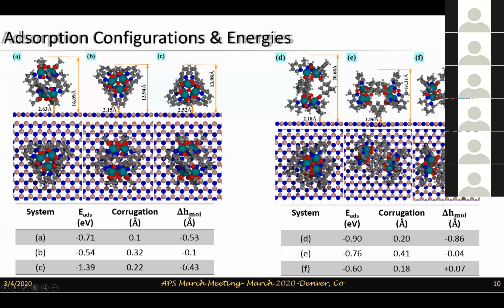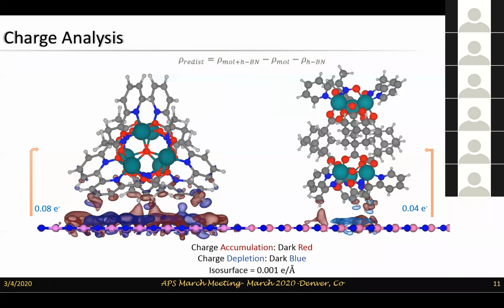I see some messages. This here is basically the shrinkage that has gone on. About half an angstrom of shrinkage of this molecule, and a little bit of breathing in the case of the antiferromagnet. The other thing is that the corrugation is actually larger in the case when it is on hexagonal boron nitride, which is understandable because unlike graphene, you have boron and nitrogen over here. So there is some tendency for these strain effects to be even more important here. So these are then the positions where they like to be adsorbed.